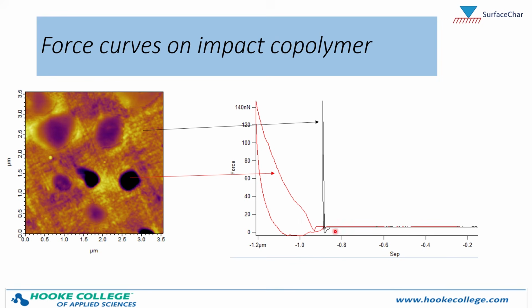analyze. So straight off the bat, there are three significant differences between these two force curves that I want to highlight. The first is the slope on this retract curve. Compare this slope with this much steeper slope here. Remember, that is the repulsive contact portion of the tip sample interaction, and this is where we get our stiffness information from our force curve. So clearly this has a lower slope, which will translate to a lower stiffness than the thermoplastic, which makes a lot of sense. A second difference I would like to point out is the adhesion.